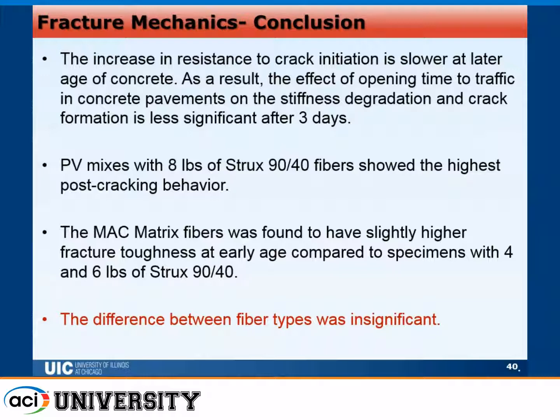However, the amount of fibers played a big role, and there was a big difference between without fibers and with fibers, and a big difference between fibers of 4 pounds and 8 pounds. The 8 pounds outperformed almost all the expectations.